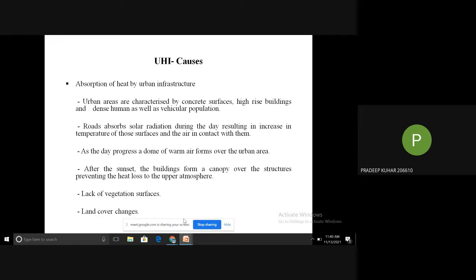Now, coming to the UHI causes part, thorough study of the literature depicts that as the day progresses, a dome of warm air is present over the urban area, and these areas are characterized by more paved and concrete surfaces, which absorb solar radiation during the day and enhance the surface temperature as well as the air in contact with them. And then in the evening, high rise buildings form a canopy over the structures, preventing the heat loss to the upper atmosphere. In past few decades, there is a decrement in the agricultural area with an increase in built up area and also reduced area for water bodies. So all these land cover changes would certainly lead to UHI.